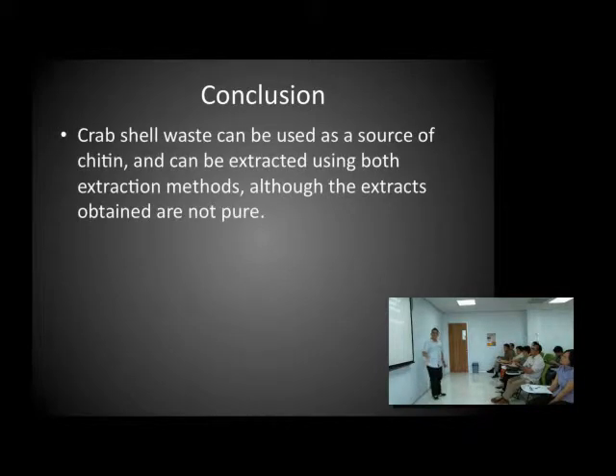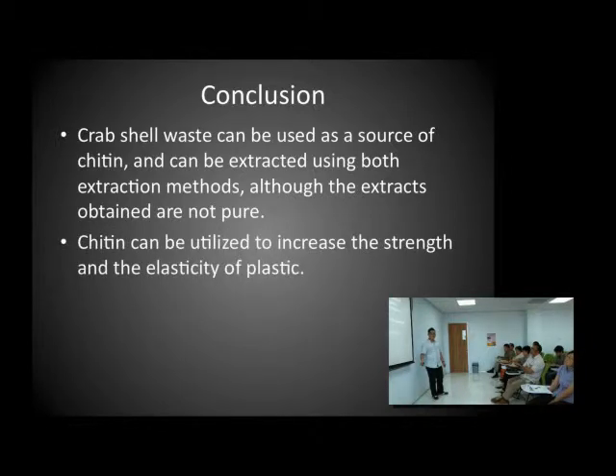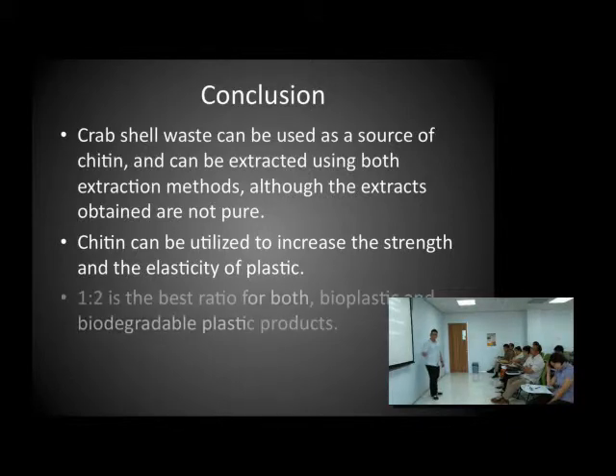So the conclusion is, first, the crab shell waste can be used as a source of chitin and can be extracted using both extraction methods. However, the extraction methods have not worked effectively because the extracts are not pure. And chitin can be utilized to increase the strength and the elasticity of plastic, with 1:2 being the best ratio for both products, bioplastic and biodegradable plastic. And the last one, I made a new hypothesis that chitin may increase materials' resistance to water through observation. So I observed this possibility.